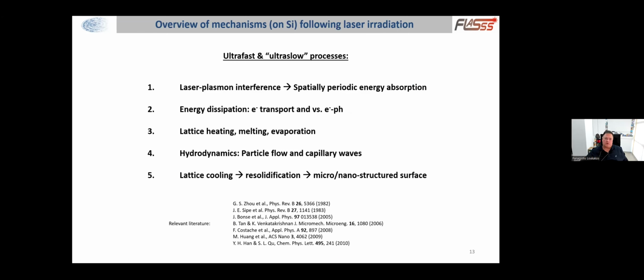In order to give an overview of the mechanisms that one has to take into account in order to have a good description of all the mechanisms that take place following the irradiation of surfaces: first we have the laser plasmon interference, which results in a spatially periodic energy absorption on the surface. And then after this, we have energy dissipation mainly via electron transport and electron-phonon interaction. These are two competing mechanisms, with electron transport tending to take energy away from the irradiated surface and into the bulk, and the electron-phonon mechanism tending to localize the energy in the vicinity of the irradiated surface.